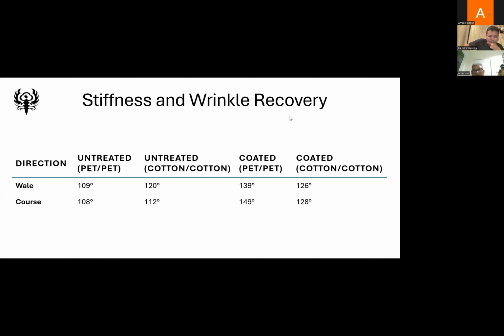And the last one is stiffness and wrinkle recovery. We can see from the angle of the test that the fabric before and after treatment, in both wale and course directions, increased. That means the fabric recovers better from wrinkles.